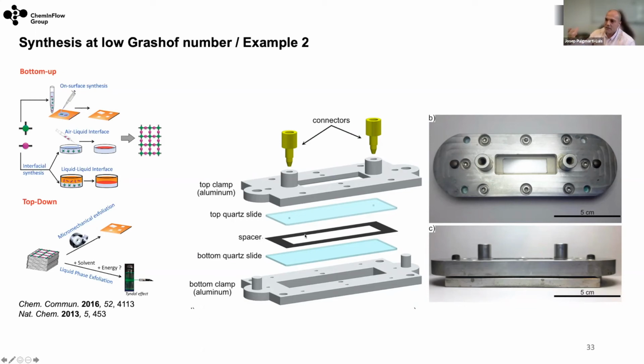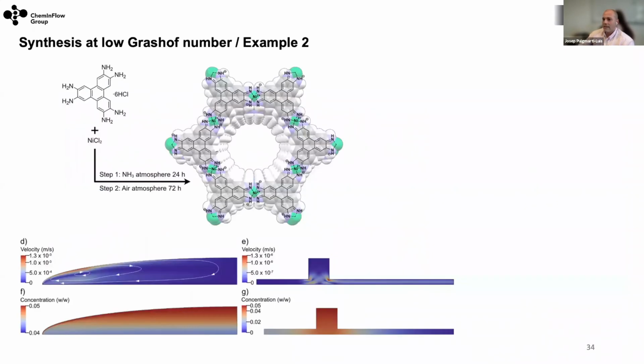We wanted to achieve, or simulate, the conditions that you will have at the International Space Station. And this is what we started to do. So we started to generate this 2D, very well-known 2D MOF that is a conductive one. Normally this is generated with what we can call a droplet approach. So you have the precursor in a droplet, and then you treat this droplet, and you then generate, in this case, the conductive MOF.